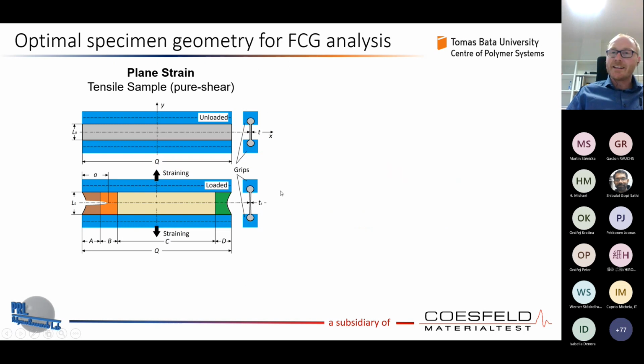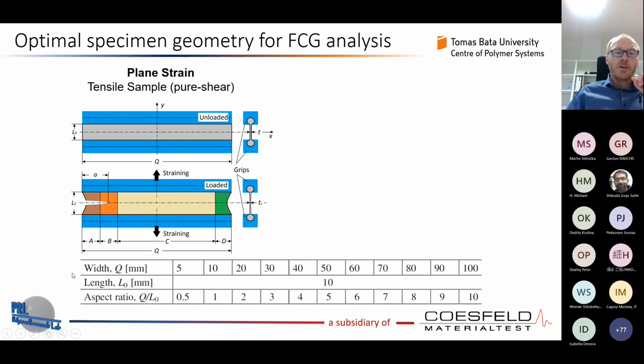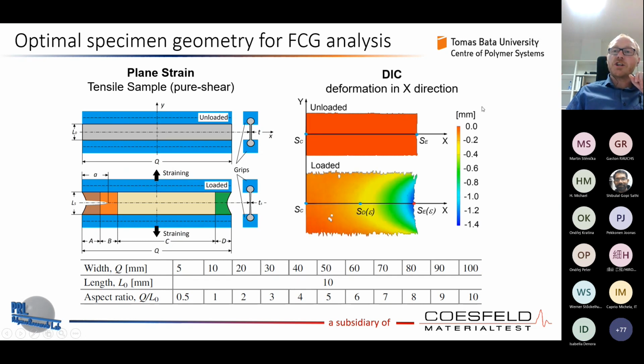So in the next paper we presented with a colleague in the book, we investigated this phenomenon on different aspect ratios. That means the aspect ratio of width to length, or height, of the sample from 0.5 up to 10. And we used digital image correlation to describe really the deformation fields or strain fields in the x direction, that means in the direction of the width.